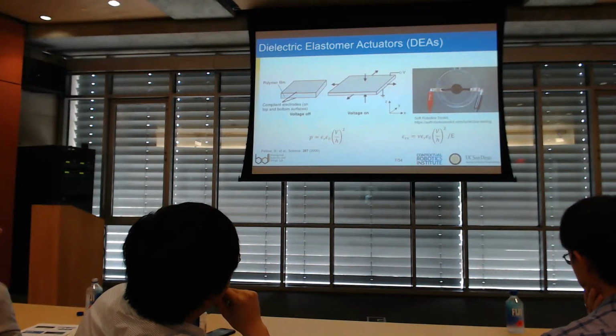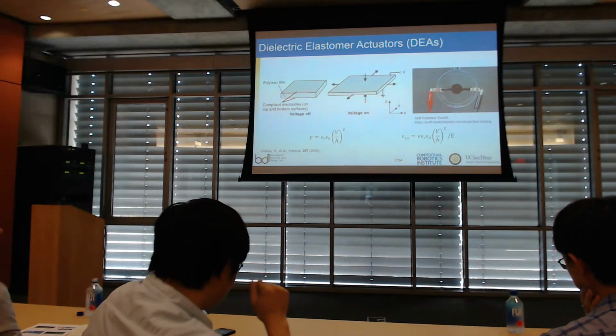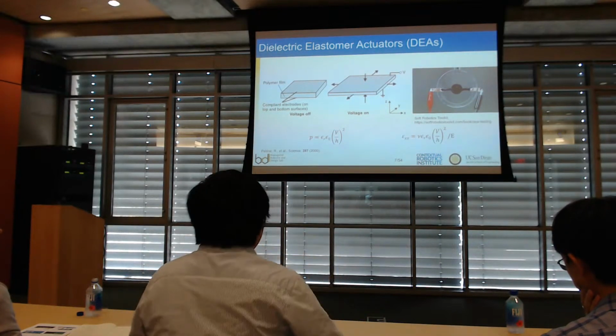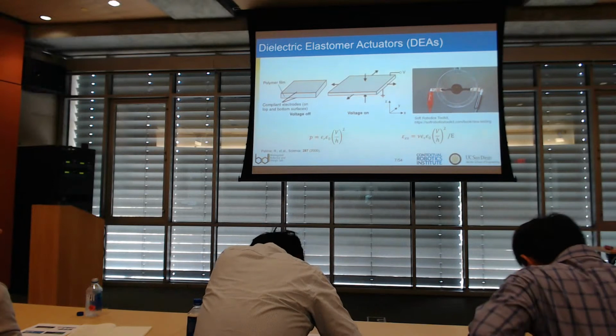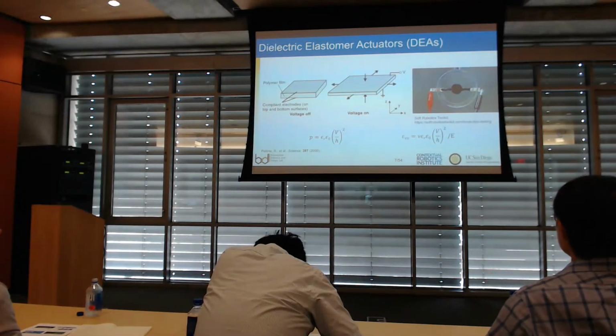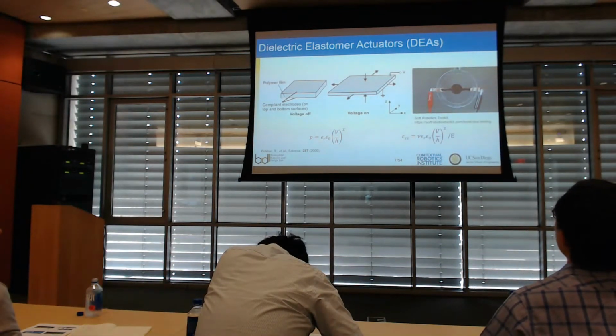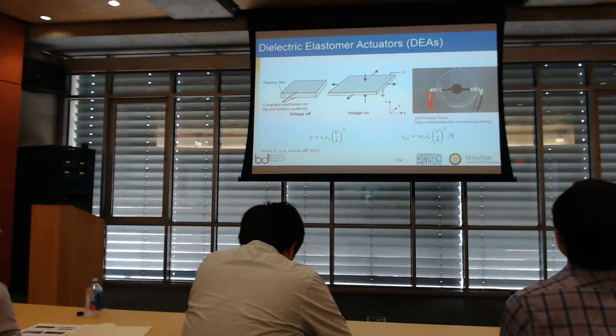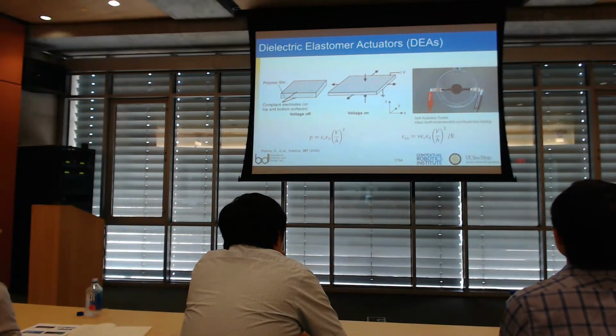But the voltage that you can apply is limited by the breakdown strength of the material. So like how much voltage can the material take before it sparks and so it breaks down. And then the thickness of the material. So the materials that we work with are usually anywhere from, say, 50 microns to a millimeter in thickness. And then the Young's modulus is something else that we can select for.